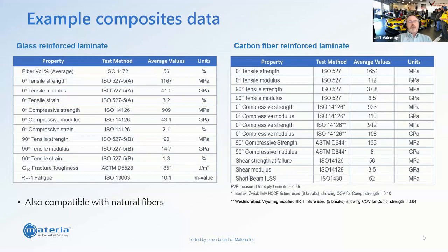Again, I'm not going to go through all this data, but the point of putting this data in here is, again, remember I mentioned that Proxima can be used with reinforcements, whether it's glass, carbon fiber. We've also done a lot of work with natural fibers. We don't have that inherent issue with the traditional DCPD materials, where our catalyst doesn't have any adverse reactions with any of the reinforcements. You can see on the left, this is a glass reinforcement laminate that we did for a customer. And then on the right, a carbon fiber laminate that we produced.